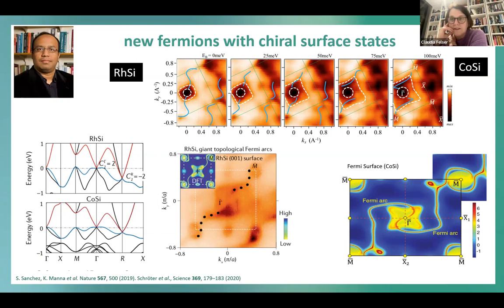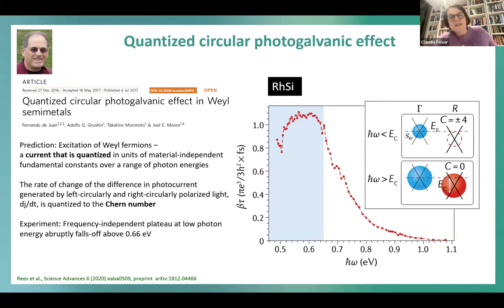We did the first steps here, and Christina has to click again. Oh no, this is something. There was a prediction also that you see, it's always the most convincing thing if you see a quantized effect, okay? So the big thing why mercury telluride got so much attention is also because they saw a quantum spin Hall effect. So when Joel Moore did the prediction that these materials would show a quantized circular photogalvanic effect, we were looking for this, and we see a kind of rough plateau, but it's not very nice in rhodium silicide. I would say here we have to do more work.